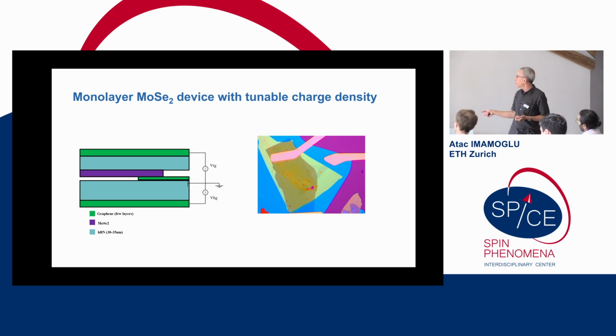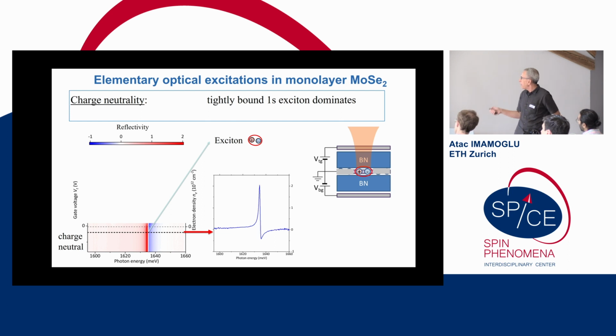So to that end, first we consider a very simple structure. We have top and bottom gates and a TMD monolayer, molybdenum diselenide, sandwiched in between, and this is the optical micrograph. If you choose the gate voltages such that the material is free of charges, then as you tune your laser field, or in this case white light, across the resonances of the system, there is one prominent resonance, and that's the 1s exciton. And this results in a relatively strong reflection signal from the material.